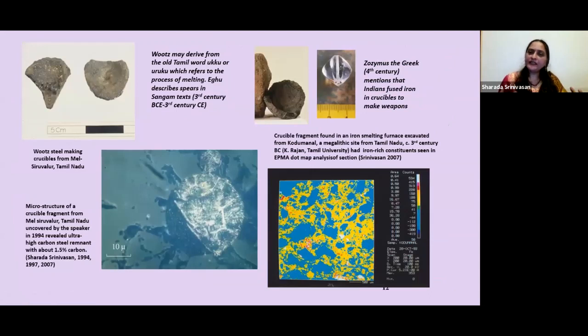And one of the early sites of production is also very important in understanding the production mechanism. Basically, a low carbon wrought iron was being carburized by placing it in crucibles along with carbon-rich material. I was able to identify some sites, for instance, Melsirivalur, where the cross section of the crucible shows that classic composition I just described of the ultra high carbon steel, pearlite alternating with white cementite, which was used to make these famous Damascus blades.